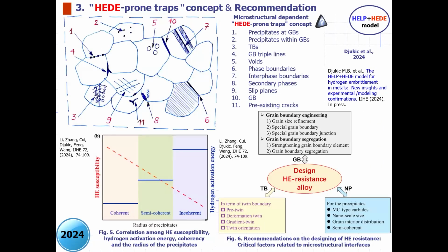HEDE-prone traps tell us what positions in the microstructure are prone to decohesion. So here is the list of locations. As you can see, various precipitates, phase boundaries, interface boundaries, secondary phases, slip planes, grain boundaries, and pre-existing cracks are HEDE-prone traps. So when we do metallurgical engineering of a material, we must carefully engineer it to provide high strength by precipitation hardening and other mechanisms, but not to introduce dangerous hydrogen embrittlement-prone traps where the decohesion phenomena will appear.